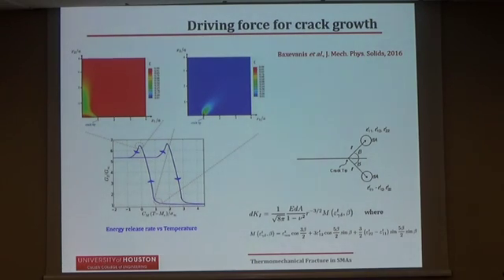Okay, so if you see here in this plot, this is normalized temperature and this is normalized driving force for crack growth. The driving force is normalized by the driving force coming from the mechanical load alone when we apply the mechanical load at a high temperature. So that's why it has a value equal to 1. Now we start cooling the material. As we cool, nothing drastic happens until we have extended phase transformation. We are in this case, so the material starts transforming in the far field, although now it has a very small value. But now almost the whole material starts transforming.